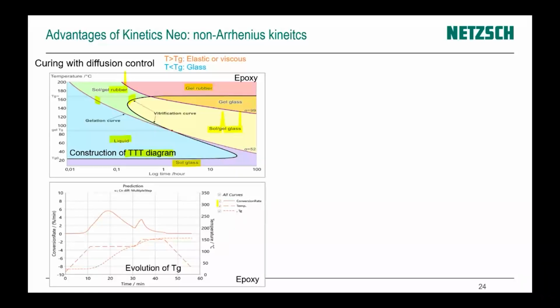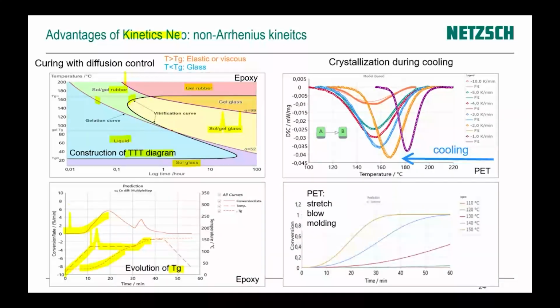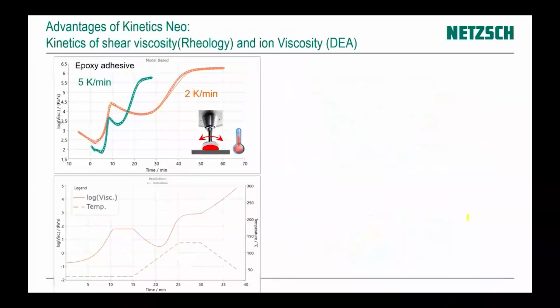We can make the predictions according to the temperature, complex temperature program, not only for DSC or for conversion rate, but also for evolution of the glass transition. In this case, only Kinetics Neo is necessary, and Kinetics Lite cannot do this. Crystallization during the cooling and, for example, isothermal crystallization close to the glass transition. Kinetics Neo can do some things which are impossible in kinetics, like, for example, kinetics of shear viscosity.